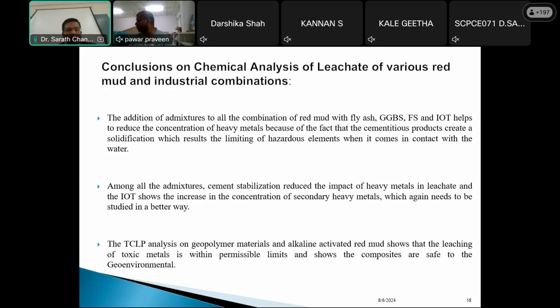Among all these admixtures, cement stabilization reduces the impact of heavy metals in leachate, and IOT shows an increase in the concentration of secondary heavy metals, which again needs to be studied in a better way. That's what I said: with IOT, though the concentration of primary heavy metals was reduced, the secondary heavy metals, which are other hazardous materials, increased. So that needs to be addressed, because sometimes even though one concentration is less, another concentration increases. As I told you earlier, I have chosen only 8 chemicals or 8 analytes because of various parameters.